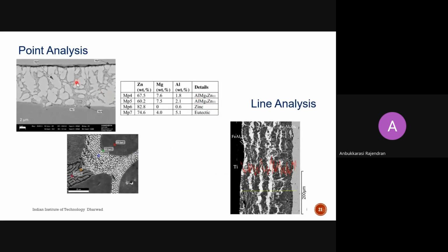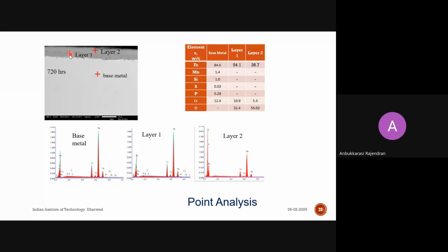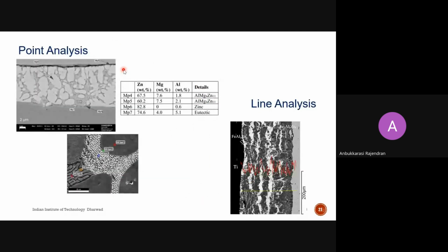It showed the variation in the composition. As I mentioned, if it is a metallic coating, it has a uniform composition throughout the layer, and there is only a composition variation between the layers. But here, within the layer itself, there are multiple phases due to the different composition and the way of coating. So I have to select each region to understand what phases it could have. So this is the point analysis. I can even select an area of this entire phase, so area analysis also I can carry out.